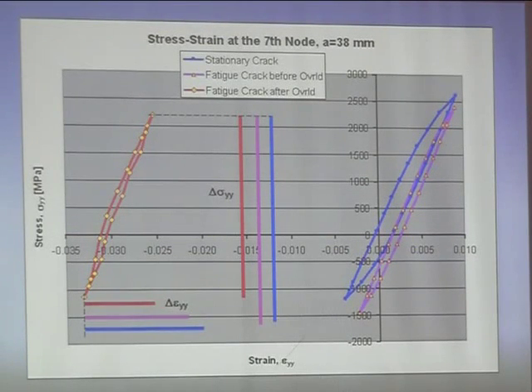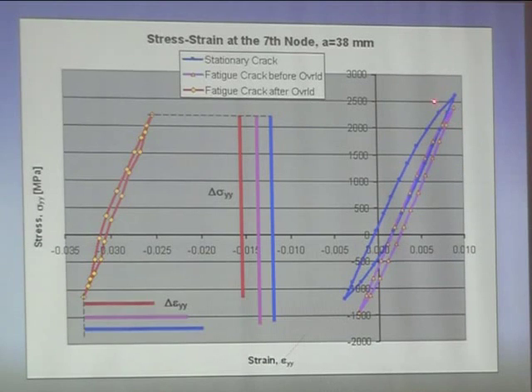So I said, okay, let me go now to these 3 cases. I took the hysteresis loop at 7 nodes, even further from the crack tip, in order to get to kind of reasonable strains and stresses. And I compared the hysteresis loop for identical cycles for the stationary crack, the fatigue crack before overload, and the fatigue crack after overload. And what you see is that the stress ranges, as you see, the blue one is the stationary crack, that one is the constant amplitude fatigue crack, that the stress ranges are almost the same, and even the strain ranges don't differ, but these are mostly elastic strains, where here there is a lot of plasticity.